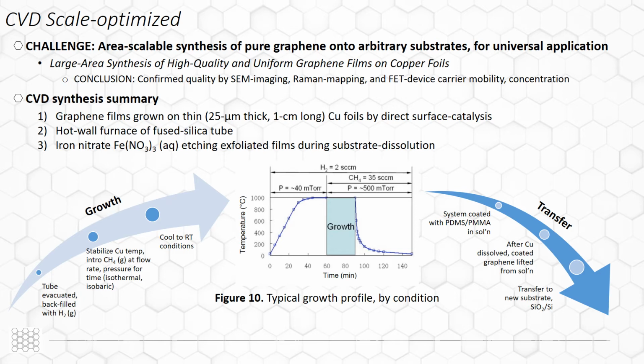This effective etching interval was determined by etchant concentration as well as foil area and thickness. Usually, a 1 square centimeter, 25 micrometer thick copper foil was dissolved by iron nitrate overnight, but at low concentrations of 0.05 grams per milliliter this took about 16 hours overnight. This chemical exfoliation process collected 2 films from both sides of each copper surface.